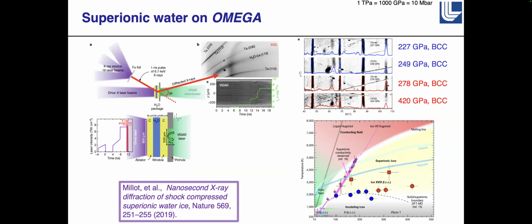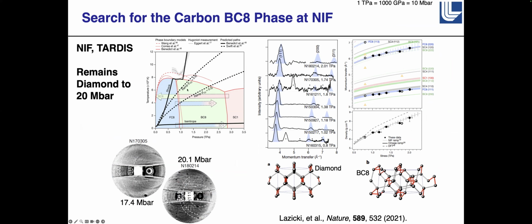What we're doing is that we've done MD simulations with Ivan Oleynik at the University of South Florida, who's doing these huge billion atom simulations. Sandro Scandolo back in the 90s predicted that it would be very difficult to do this because on average you have to break over 3 bonds, so it's a highly reconstructive transition. It takes a lot of energy. What Ivan found was that when he gets this transition to go, it actually melts before it freezes. If you extend the melt line, simulations agree that diamond should melt at a lower temperature than BC8 should melt.